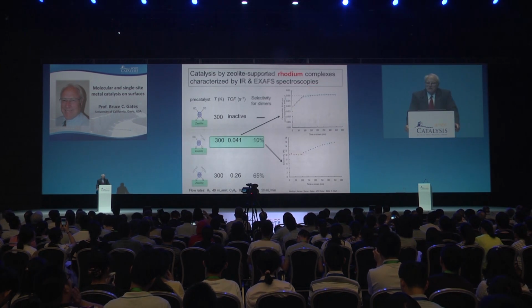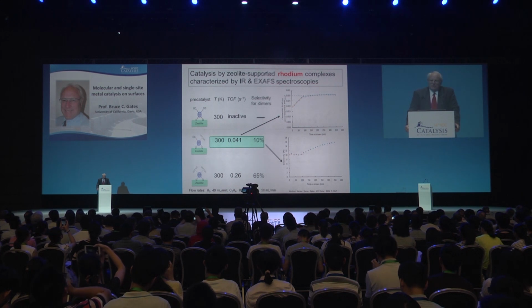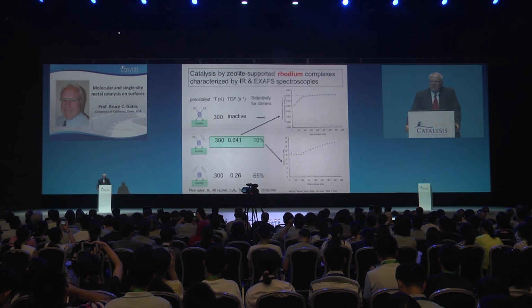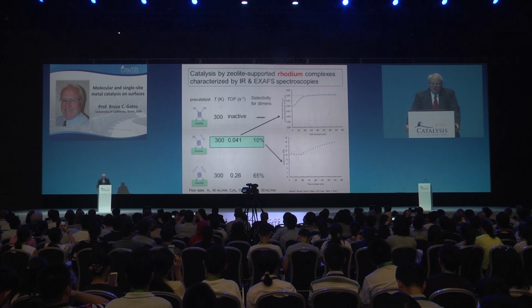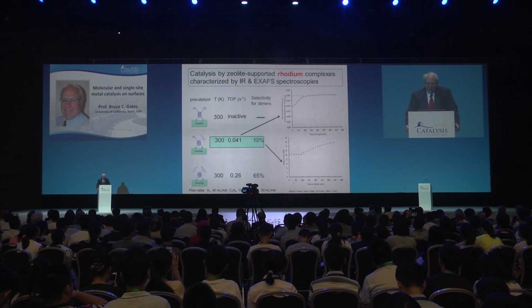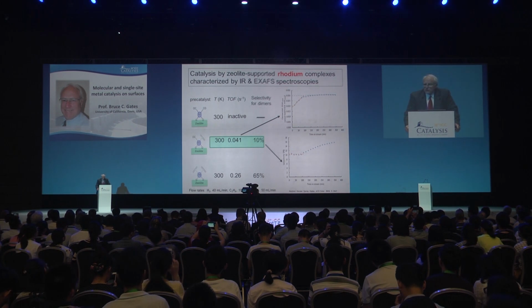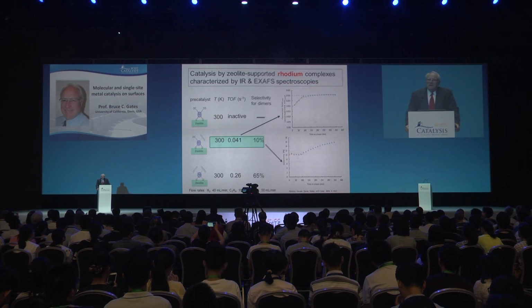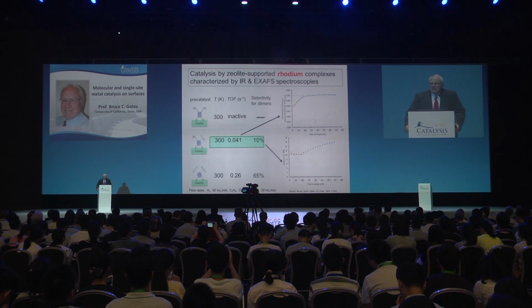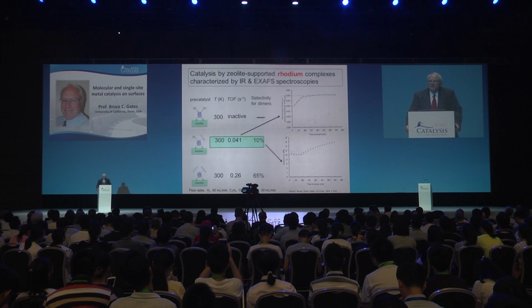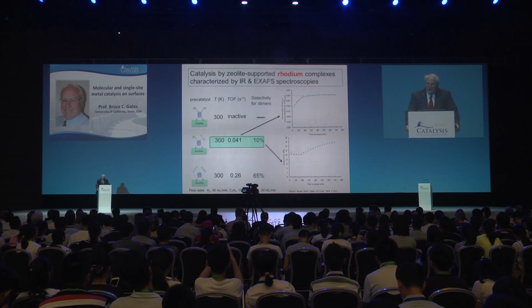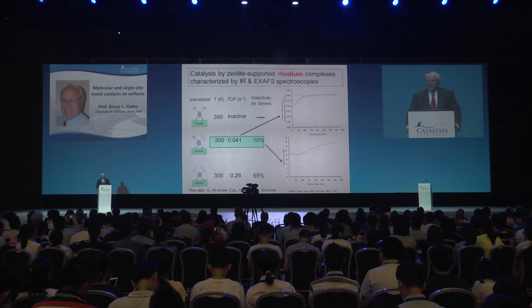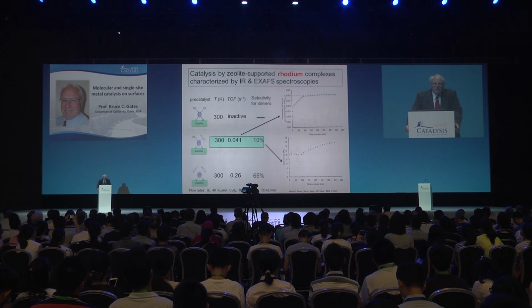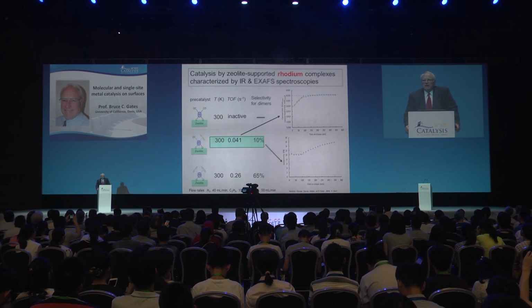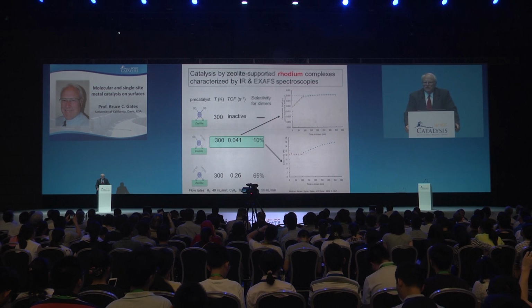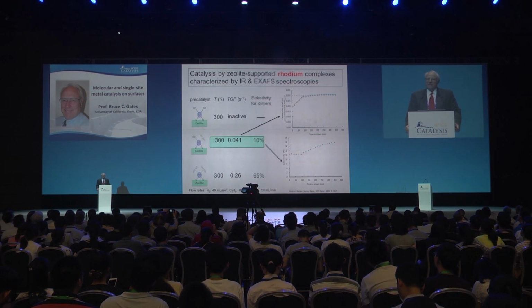In the upper right, what you see is conversion plotted as a function of time on stream. The conversions are very low, differential. The conversion changes with time on stream because the ligand environment of the metal changes as it is operating. So we're extrapolating to the initial condition, and it's not quite kosher to do that because, of course, we must